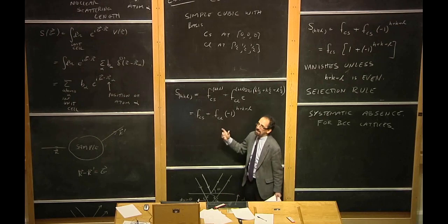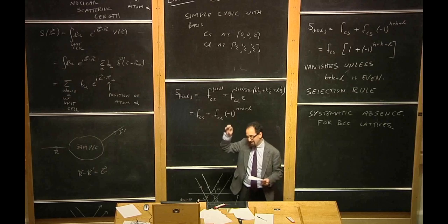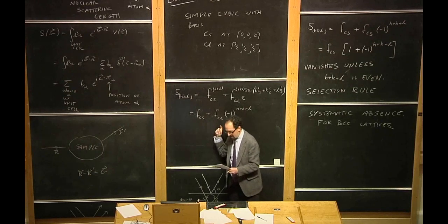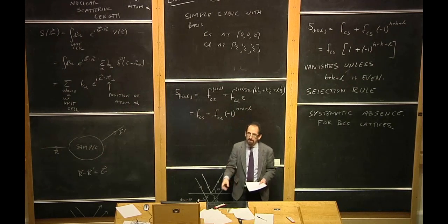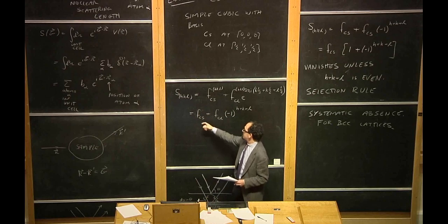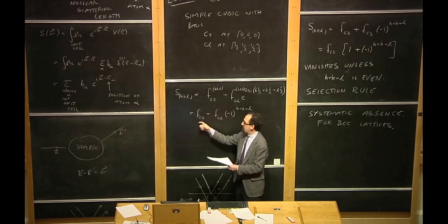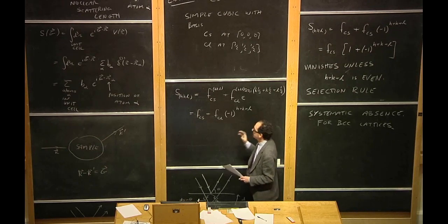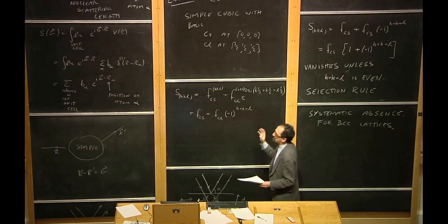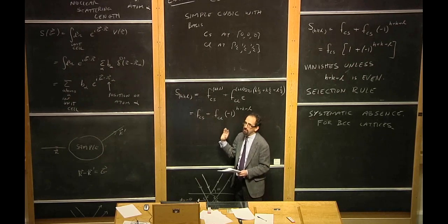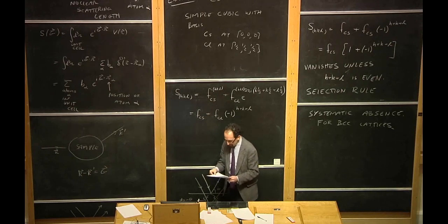It's cesium iodide. If you replace chlorine with iodine, which is two spaces under it on the periodic table, the iodine has atomic number 53 and cesium has atomic number 55. So the cancellation between these two would be almost exact. I mean, only within a few percent you would have a slight non-cancellation. So it's very easy to make the mistake and look at the data and think that you have a BCC lattice because you think there's a systematic absence. But if you look at it much, much more closely, you discover that, in fact, it's not perfectly canceling. Okay? Everyone happy? All right.